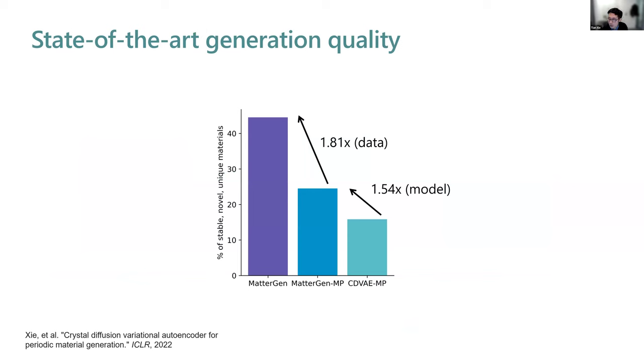So, with this metric, we show that MatterGen is actually state of the art in generation quality compared with the previous state of the art, CDVAE. So in here, we actually disentangled the improvements for model and data. For the model, both trained on MP20, MatterGen was 1.5 times better than CDVAE, while the other 1.8 times performance improvement comes from the much bigger training data.